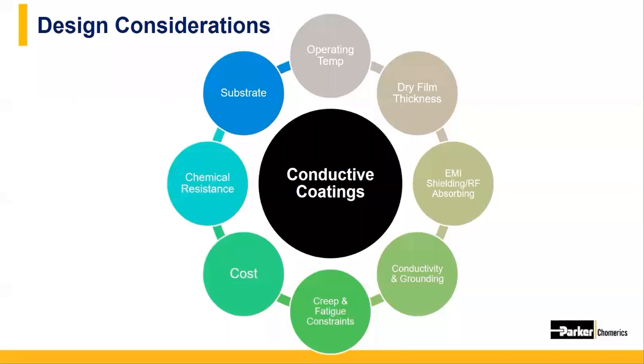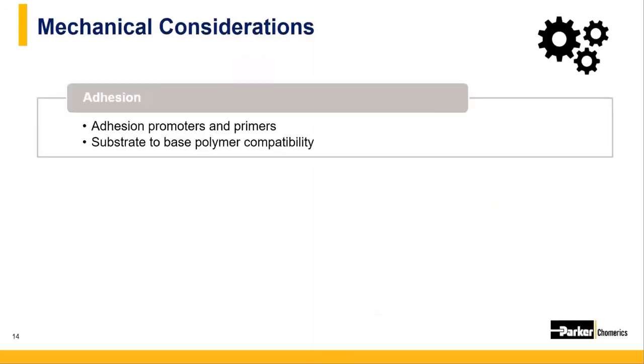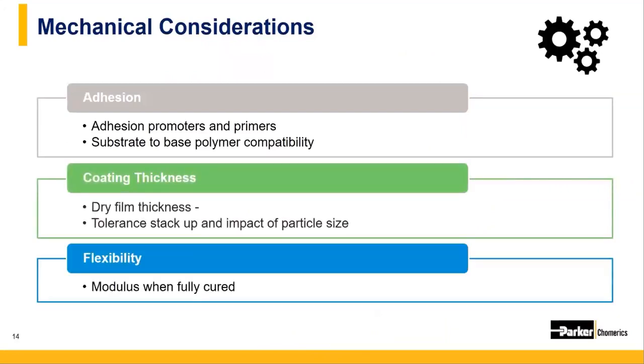The polymer-based material should be chosen based on the type of substrate, the operating temperature, chemical resistance, and other requirements for coatings, which can include UV protection, impact or shock loading, and wear limitations. These issues can come back fierce and can really add complexity to fixing your design when and if it fails EMI and you didn't consider these things up front. A few of the mechanical considerations to consider when planning conductive coatings are adhesion strength, coating thickness, and flexibility.